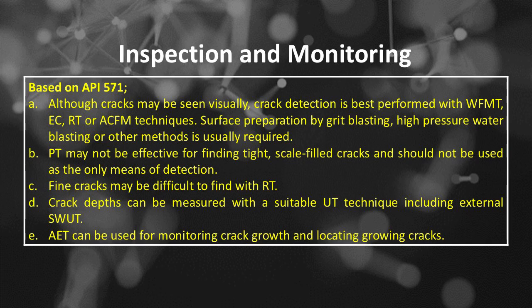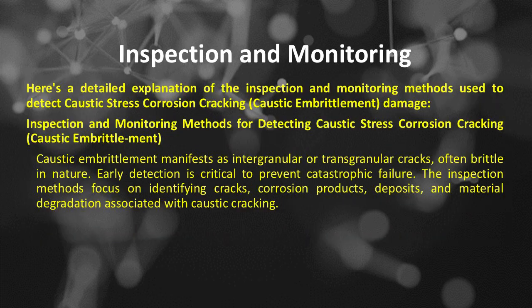Number D, crack depths can be measured with a suitable UT technique including external SWUT. Number E, AET can be used for monitoring crack growth and locating growing cracks. Here's a detailed explanation of the inspection and monitoring methods used to detect caustic stress corrosion cracking or caustic embrittlement